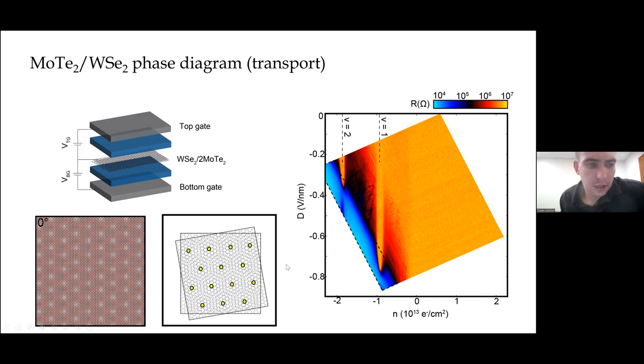So anyway, the TMD heterobilayer lattice is shown approximately to scale on the bottom left. These systems have both a bottom gate and a top gate. One of the advantages of the SQUID over other scanning probe microscopy techniques is that we can see right through the top gate, right? So there's no meaningful screening of the magnetic field by the graphite top gate, which means that we can easily see what's going on inside.